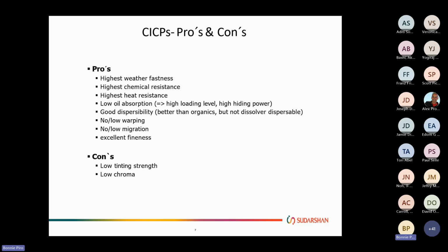However, they are hard particles, so they're not really good candidates for just dissolver types of dispersion processes. On the plastic side, they typically have no or very low warping and migration, and they also have excellent fineness when they're ground in a liquid environment.